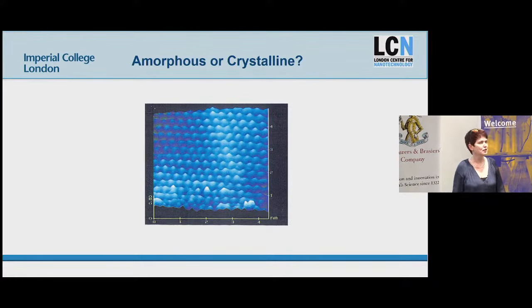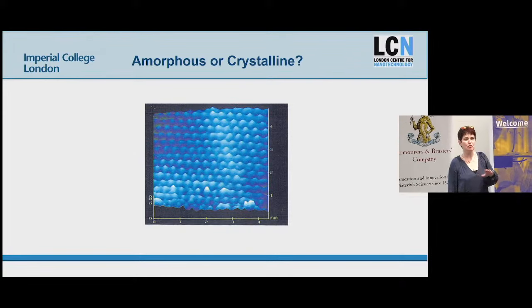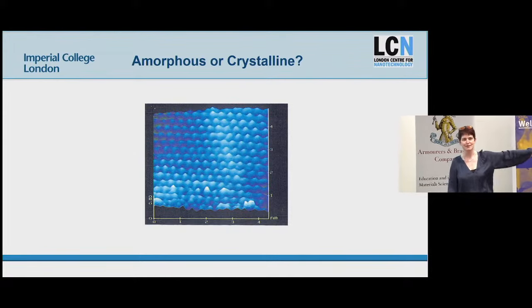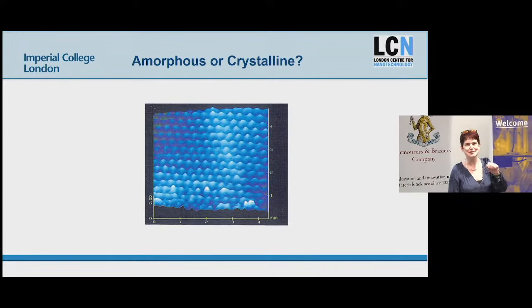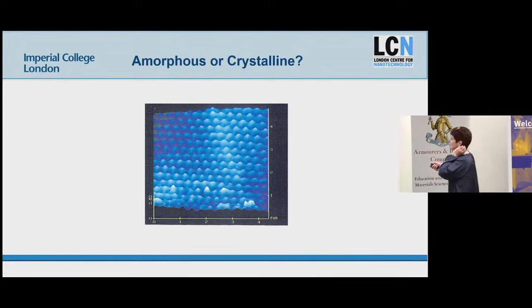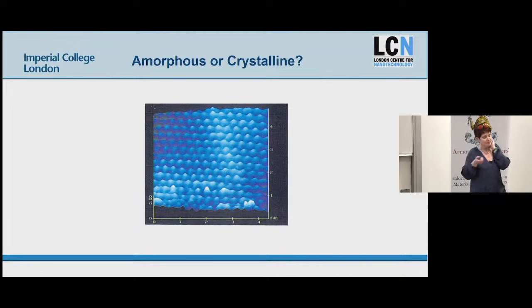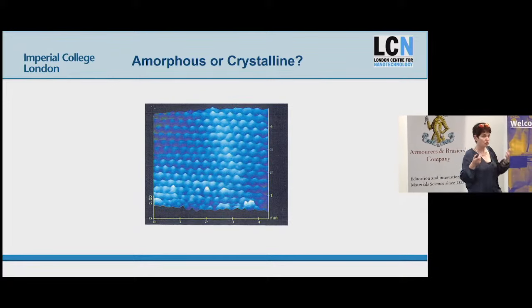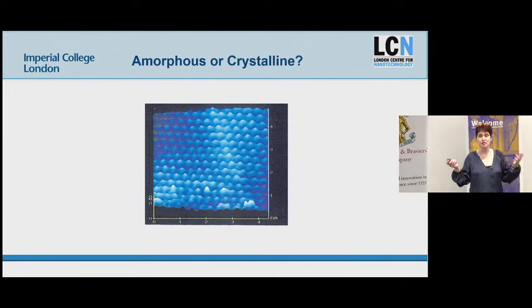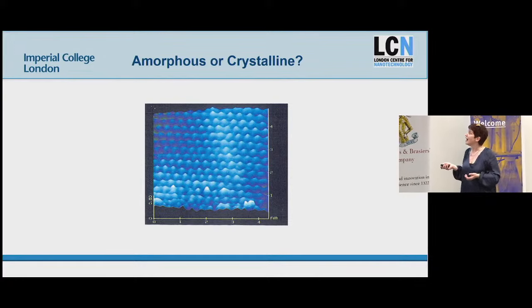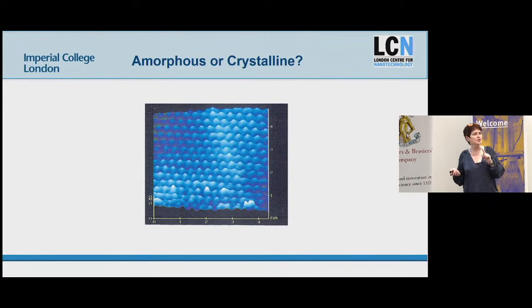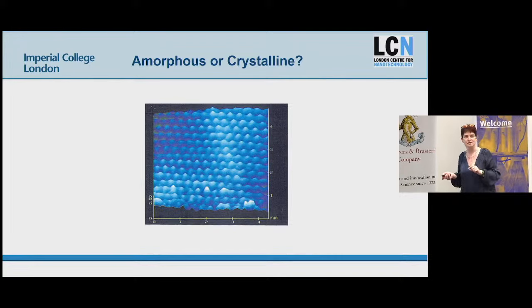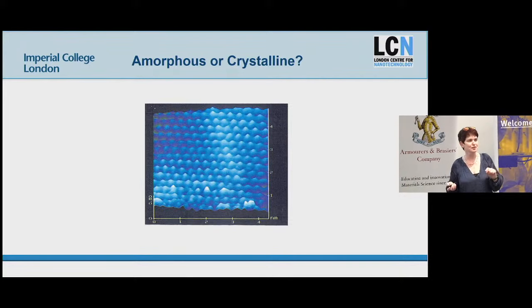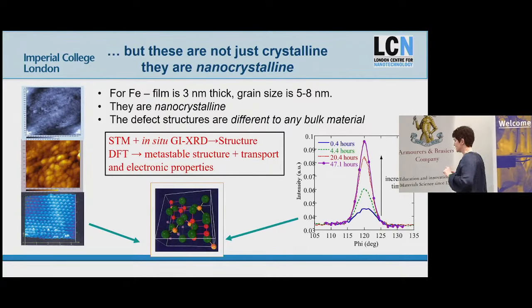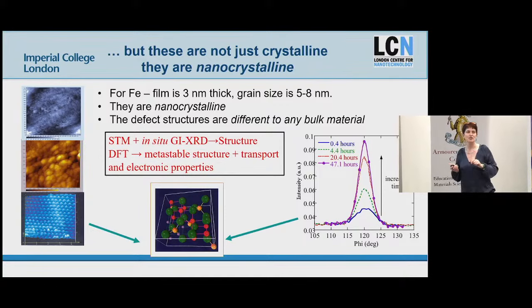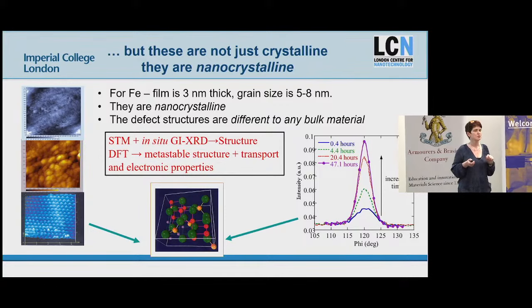And you kind of go, okay. I wasn't quite arrogant enough just to put one picture in and say I've done, right? No. That probably wouldn't pass. But it's crystalline, and STM, this technique that we were using, showed that really clearly, right? It's a crystalline material. And so it turns out that isn't what's interesting about passive films. Not the most interesting, anyway. What's the most interesting is that they're nanocrystalline. Right? So what does that mean?